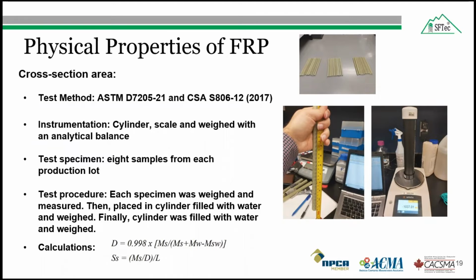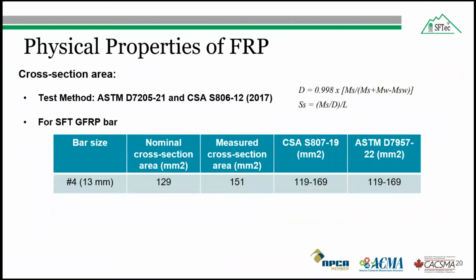So the cross-section area or the specific surface in square millimeter was calculated using this equation: SS is equal to MS by D, divided by L. And in this case, SS is the cross-section area and D is the density of the specimen, which is calculated using this equation, where 0.998 is the density of water at room temperature, and ms is the mass of the specimen, mw is the mass of the water in the cylinder, and msw is the mass of water and specimen in the cylinder, and L is the length of the specimen. So for the SFTec glass fiber reinforced polymer bar number 4, the average measured cross-sectional area was around 151 square millimeter. The nominal was 129 square millimeter. And this area was greater than the required CSA S807 and ASTM D7957.